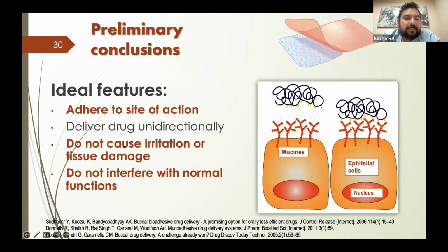We already tested that these fibers do not cause any irritation or tissue damage in vitro, in cell lines, fibroblasts, and blood cells, and in hamsters, in the oral cavity of the hamster, and with the acceptance test in human patients, we see that they do not interfere with normal functions.